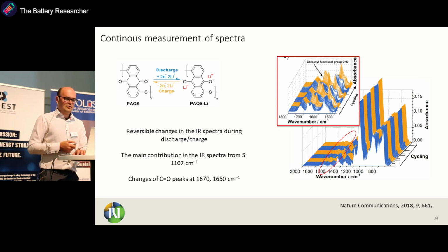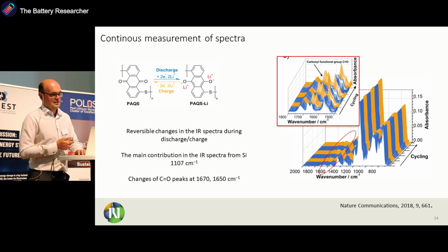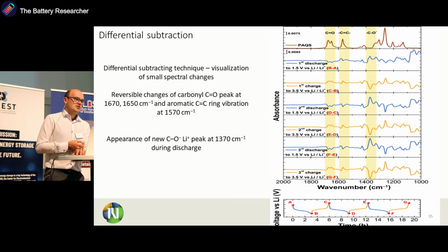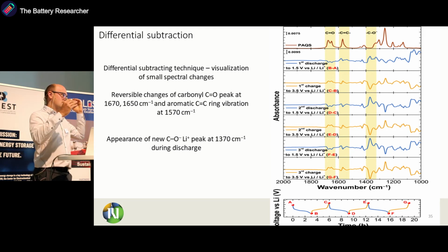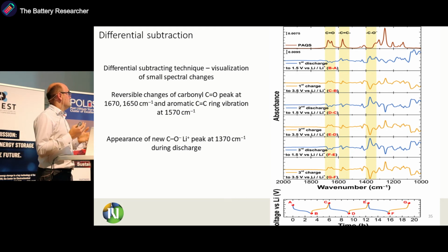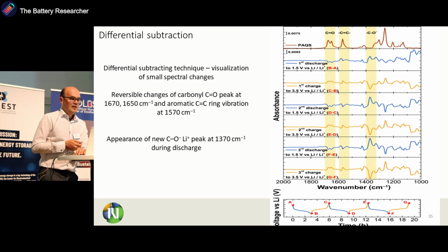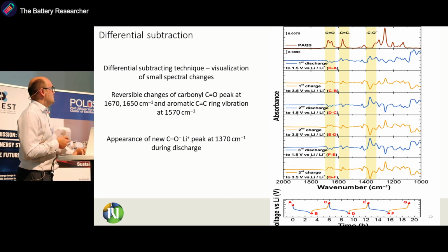But we said, okay, can we do this a bit better? And we decided to do differential subtraction. So basically taking the spectra at different points and subtracting them from each other to remove all the non-active parts. And here we can see that we now see much better. We see again this carbonyl going up and down during discharge. But then we also reveal this C-O minus peak, which is here, appearing in discharge and disappearing in charge.